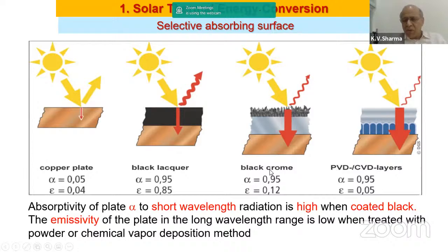Now, when we go for black chrome, we have absorptivity to be very high and also emissivity is about 12%. But when we go for chemical vapor deposition or physical vapor deposition, PVD or CVD method of coating an absorber surface, we see that its absorptivity is very high, of the order of about 95%, and emissivity is as low as 0.05. So we see that most of the flat plate collectors have such a type of coating which will help us to enhance the efficiency of a flat plate collector.